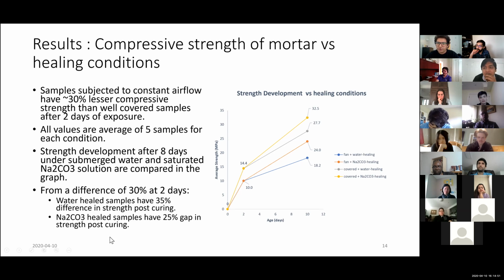So unless you know the amount of water that was present even after evaporation, and after that you cured, unless you quantify these things, it will be very hard to know whether it's coming from water, heating, or sodium carbonate. All your testing depends on this, because you need to show what is affecting your final system. So this remains an important criterion for you to quantify. In this case both were dry, but still we need to figure out the loss of water from evaporation.